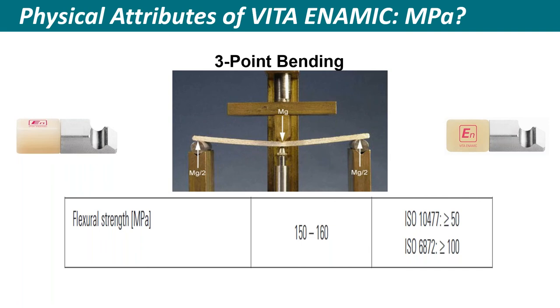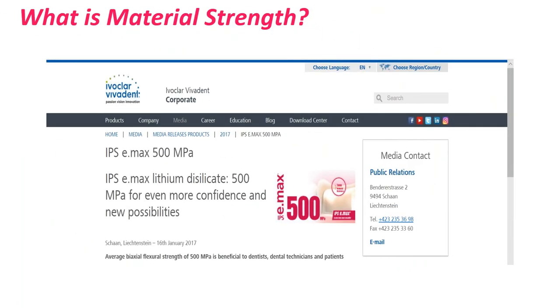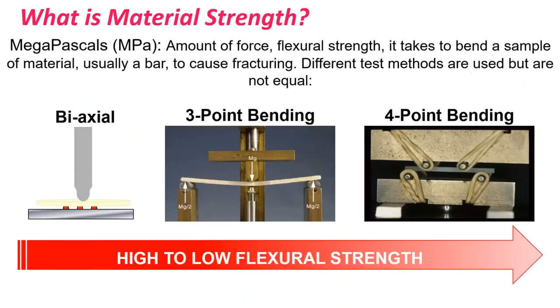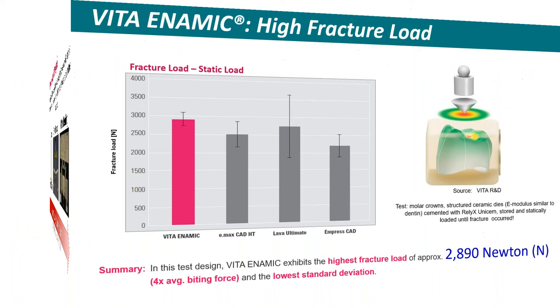But what does that mean clinically? It means absolutely nothing. If you look at a competitor material, one day overnight, it jumped from 360 to 500. How did that work? Well, I mentioned it earlier. It was a type of testing. It was moved and marketed from a three-point bending test that came out about 360 to 380 megapascals, and by changing the configuration of the sample tested to a disc, now you've got more surface area and it takes more load to actually cause it to fracture. So it's a game sometimes on the marketing side.